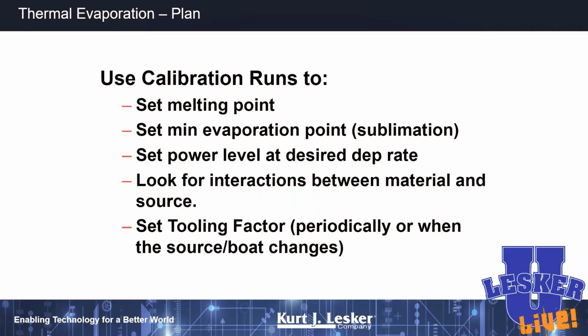We do recommend calibration runs. So if you're starting over with a new boat, or starting over with a new material, you do a calibration run. Do something onto a microscope slide, something that's not onto your precious substrates, just so you can look for melting temperatures. You can look for reactions between the material you're depositing and the boat. It'll let you set the tooling factor for your quartz crystal microbalance.